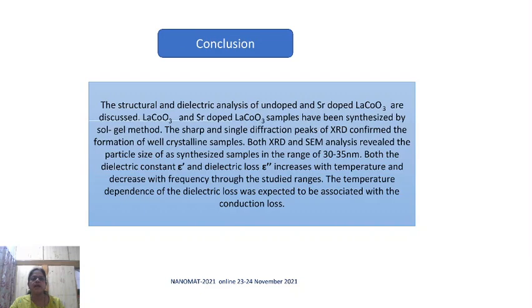Conclusion. The structural and dielectric analysis of the undoped and Sr doped LaCoO3 are discussed. LaCoO3 and Sr doped LaCoO3 samples have been synthesized by sol-gel method. The sharp and single diffraction peaks of XRD confirm the formation of a well crystalline sample.